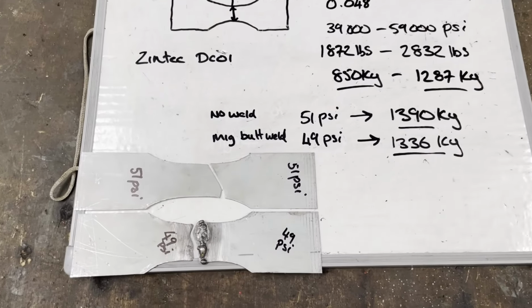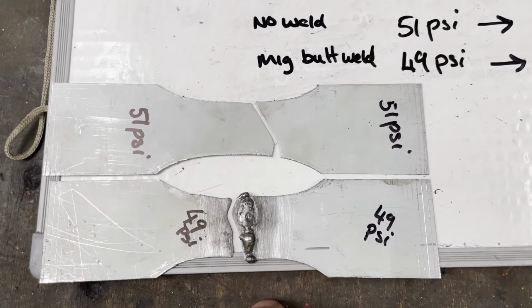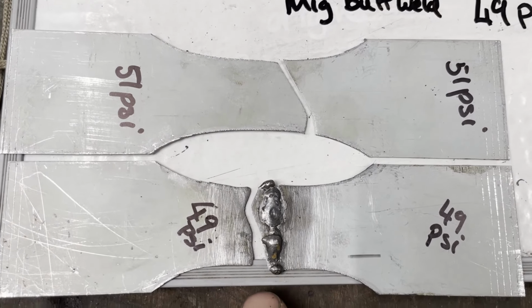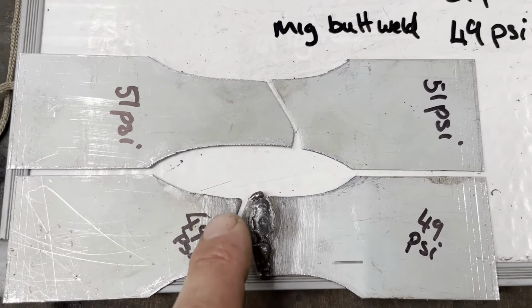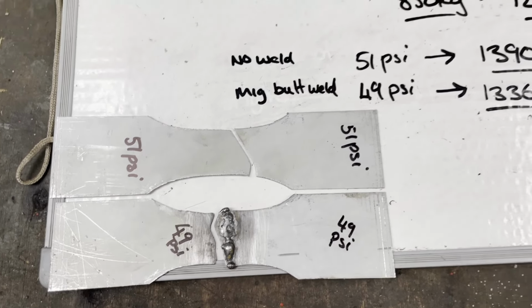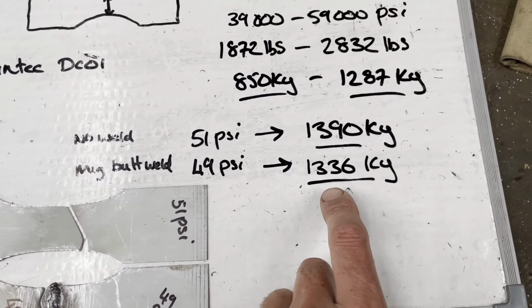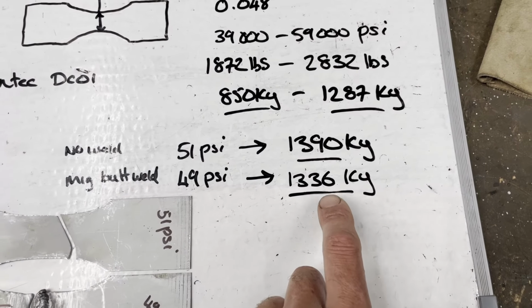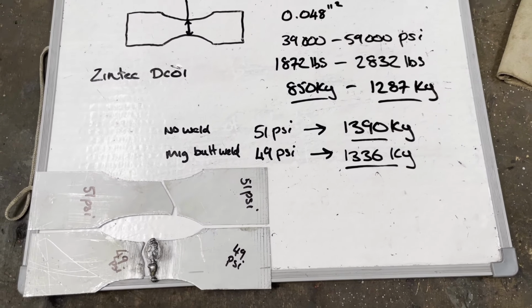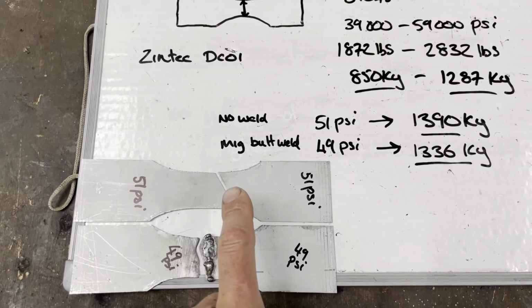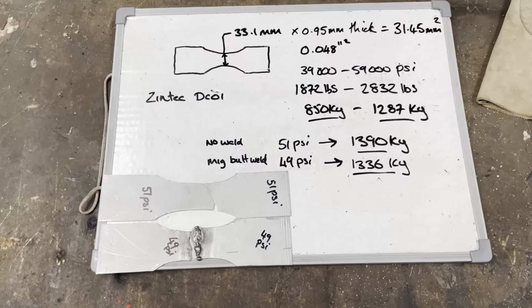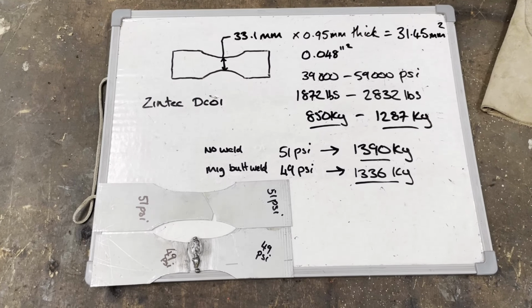The MIG butt weld then broke at 49 psi, and it didn't break on the weld, it broke back from it as you would expect. And 49 psi is 1336 kilograms, hardly any difference between that and the one that wasn't welded. Let's try a lap joint then.